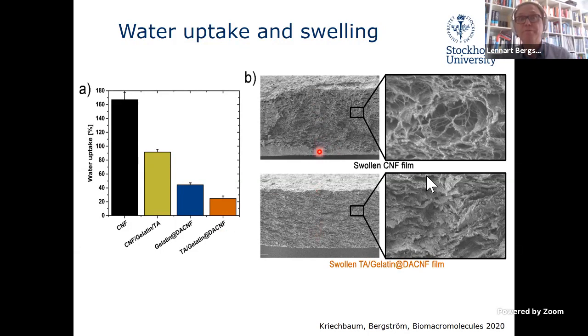And that's also reflected in the difference here of the swollen films. So the water swollen CNF films, you can see, has a very high porosity - this is crash frozen and then imaged with the SEM - while the cross section of the leather-inspired films have basically preserved to a much higher extent its laminated structure and swells much less.